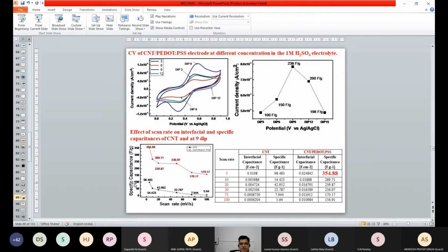And here you can see the specific capacitance against the scan rate. The lower curve is for the CNT, and the upper one is carbon nanotube coated with the PEDOT. By coating with the PEDOT, the specific capacitance is increased drastically, and we reach a value of up to 354 farad per gram by coating the polymer on this one.